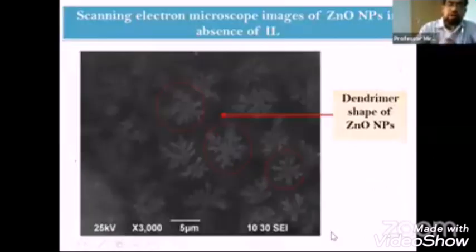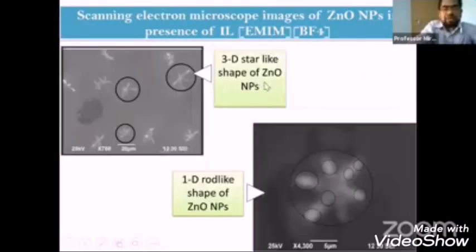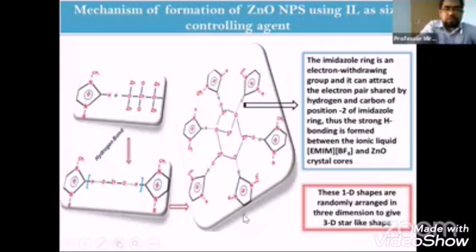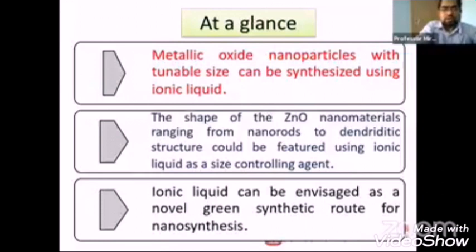Actually, I did my PhD on protic ionic liquids for use as a fuel cell electrolyte, and I am also doing research in this field. But today I am showing that we use ionic liquid for the preparation of zinc oxide. Here you can see an image when we didn't use ionic liquids. It shows the dendrimer shape of zinc oxide nanoparticles. But when we use ionic liquid as the medium, we got 3D star-like shapes of zinc oxide nanoparticles, and in one case you see 1D rod-like shapes. This is due to the possible formation of a strong hydrogen bonding network between the cation and anion of the ionic liquids. So we can say metal oxide nanoparticles with tunable size can be synthesized using ionic liquid.